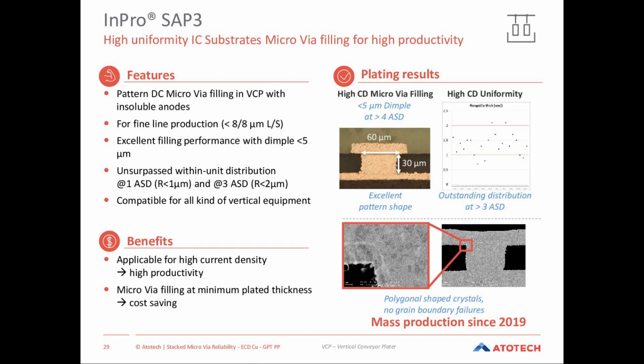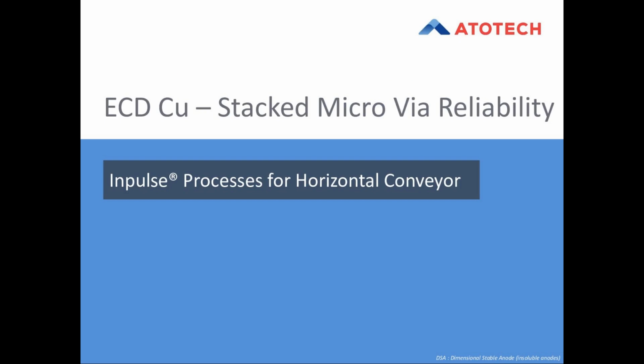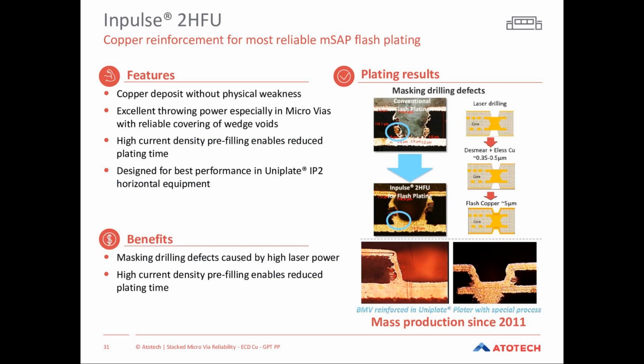Finally, for IC substrate, which is a pattern plating application in general, we have here our InPro SAP3 process, giving you really good high current densities of 3 or 4 ASD. It gives you a very good surface uniformity in pattern plating application. And on the other hand, a very nice line shape, which is nowadays also very important to control in the IC substrate application.